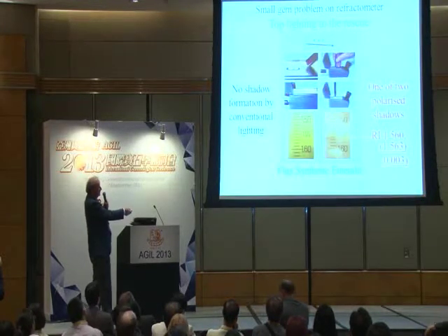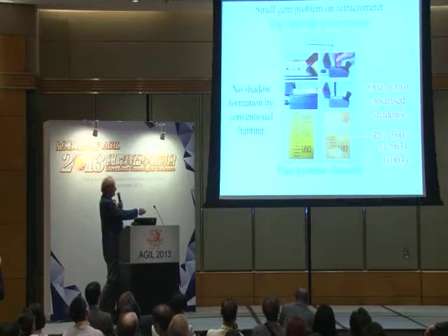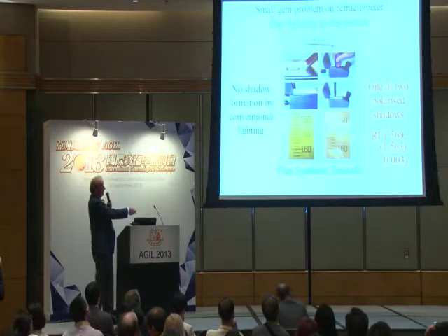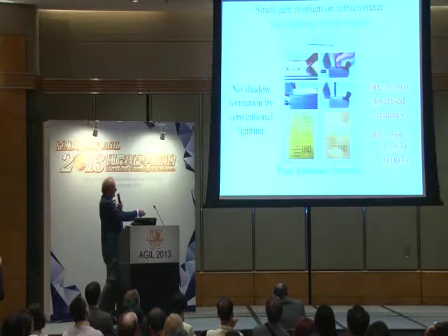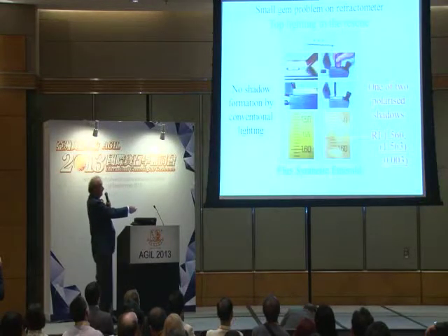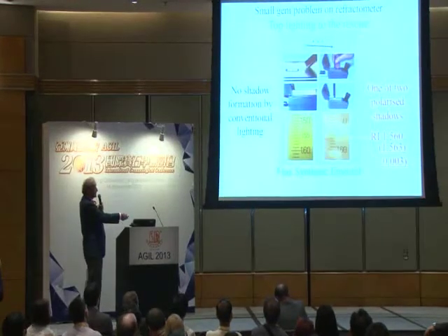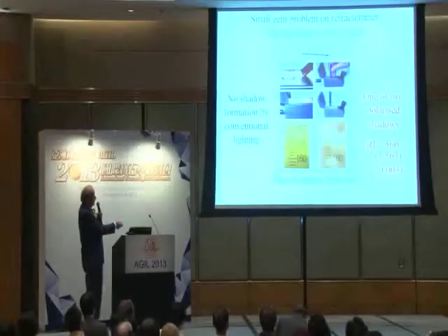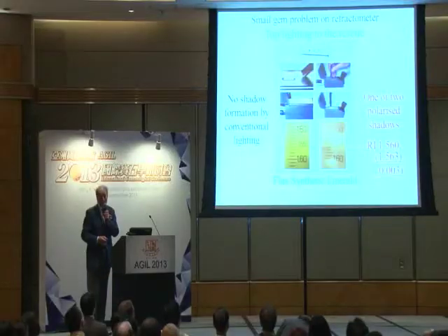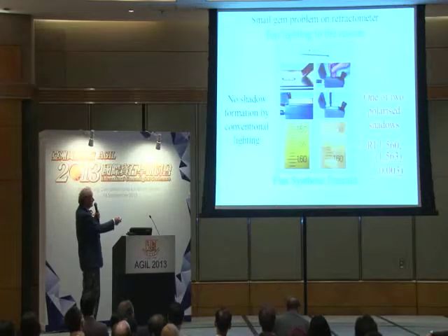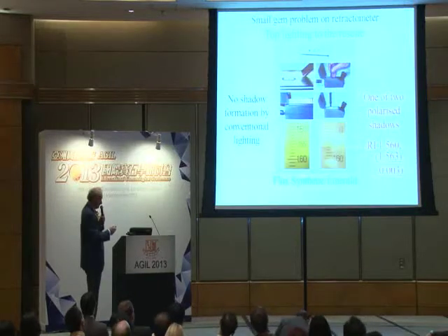This is the ordinary ray, 1.560, and then we turn the polarizer and we get the extraordinary ray, 1.563. We measure the birefringence, and we've got the whole story here, not just of an emerald, but in this case, a flux-grown synthetic emerald, by using top lighting.